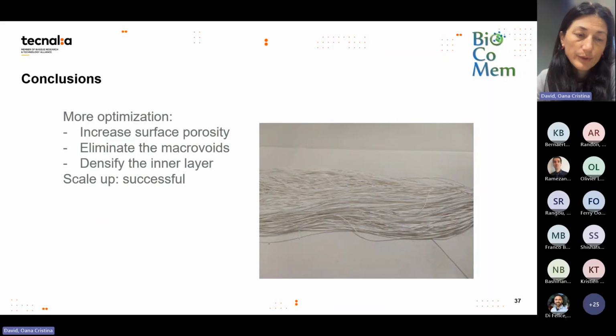And as a sort of conclusion, we still need to optimize hollow fiber membrane fabrication a bit. It seems that a dual layer approach works. We will need to increase the surface porosity to eliminate these macro voids we saw because they give low stability to pressure, and to achieve better selectivity, to densify the inner layer better. And then, even if we didn't have an optimized recipe, we did a few scale-up experiments. In 4 scale-up experiments, we managed also to achieve a successful scale-up.